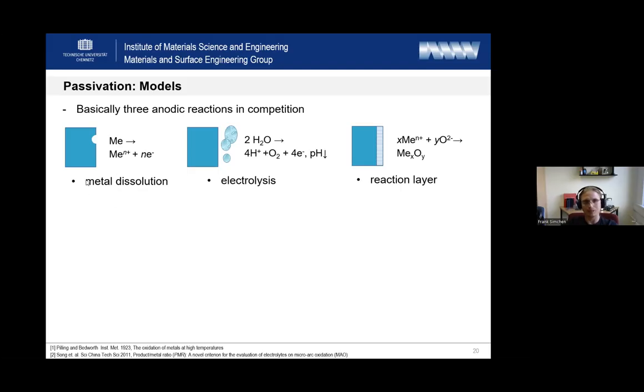So if you apply anodic polarization to a metallic substrate, you can get metal dissolution. So just metal atoms turn into metal ions and they go into liquid state and fly away. This is when you have a dissolving anode, or if the electrode substrate system is dissolving. You also can create electrolysis, which you use, for example, if you want to produce hydrogen and oxygen. And on the anode, this is combined every time by oxygen formation and development of hydrogen ions. So you get a local pH drop.